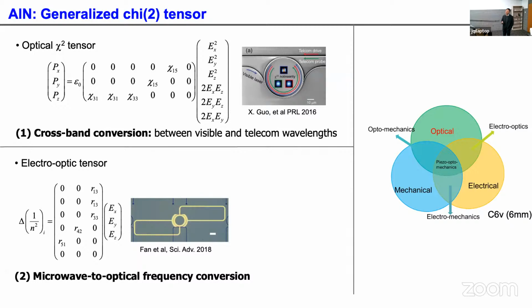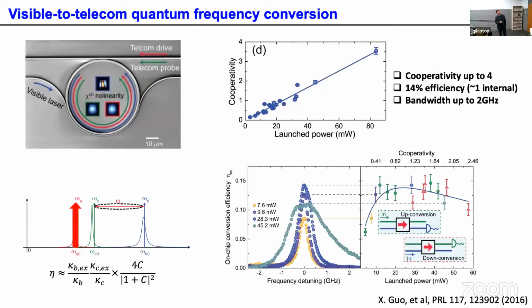So that means you are looking at the coupling between the TM modes, and our device is optimized for that. So you are converting 1550 to 780, all TM mode. The difference between frequency conversion and second harmonic generation is a little bit different, in that second harmonic generation only involves two modes. For frequency conversion, for optical to optical, we actually operate in a non-degenerate mode. One of the modes we treat as a stiff pump. They are both in the telecom regime. And when you treat this as a stiff pump, then you can get a conversion from 1550 to 780 here.